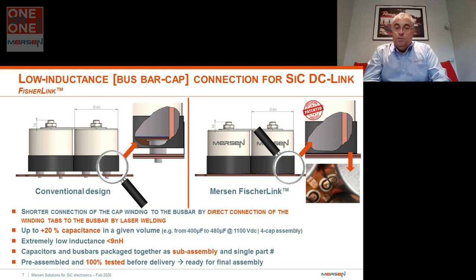Whereas with this new patented technology, the so-called FischerLink, which is based upon a direct laser welded connection of the capacitor to the busbar, we can get up to plus 20% on the capacitance in a given volume because we just eliminate the air gap, and we can get inductance as low as 9 nanohenry. That's a fantastic achievement, because here we can again shrink, as you know, the main purpose of silicon carbide: shrink the size and weight of the system, reduce the inductance, and make it much more comfortable to handle the high switching frequency of silicon carbide, even in a very high temperature environment.